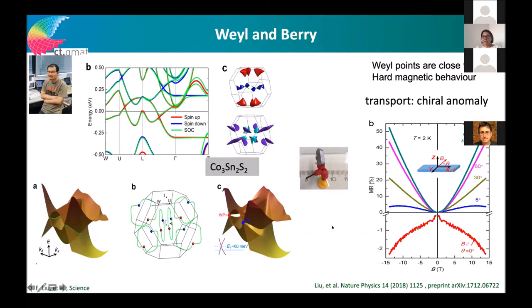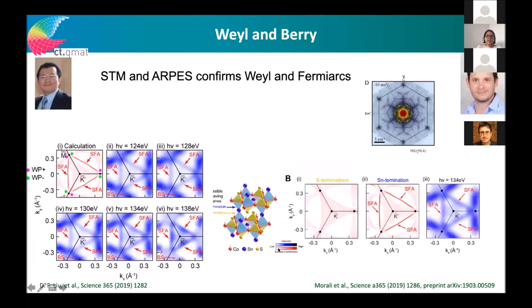Thanks to the referees, we were pushed to prove the chiral anomaly, another important feature of Weyl semimetals: with magnetic field and current in the same direction (B parallel to E) you get negative magnetoresistance, while when they are perpendicular you get positive magnetoresistance scaling with the square of the magnetization. We really found this behavior in Co₃Sn₂S₂ because of its simple band structure. The prediction was also that the Fermi arc surface states would be much larger in this ferromagnetic Weyl semimetal than in others.